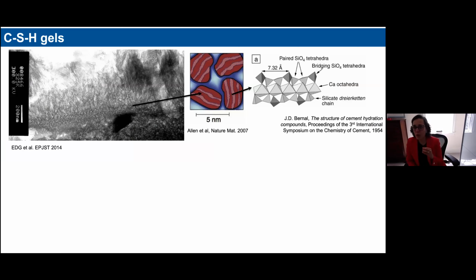So the reason why we produce this powder is that it's very reactive with water. When you mix it with water, the grains of the calcium silicates immediately start to dissolve. And from the dissolution of the grains, another material forms and precipitates. This is what is called calcium silicate hydrate, or CSH, which precipitates in the form of nanoparticles. And these nanoparticles are very sticky.